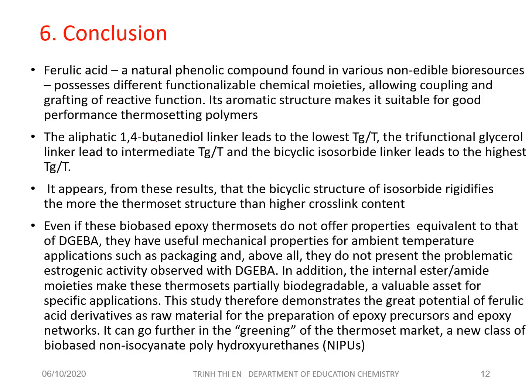And so we can go to the conclusion. The first is that from the results of the synthesis and the analysis by modern analytical methods, we can conclude that ferulic acid, a natural phenolic compound found in various non-edible bioresources, possesses different functionalizable chemical moieties, allowing coupling and grafting of a reactive function. Its aromatic structure makes it suitable for good performance thermoset polymers. The aliphatic 1,4-butanediol linker leads to the lowest Tg, and the trifunctional glycerol linker leads to an intermediate Tg, and the bicyclic isosorbide linker leads to the highest Tg because it has a rigid molecular structure, and